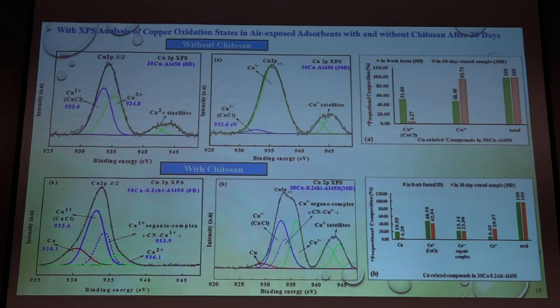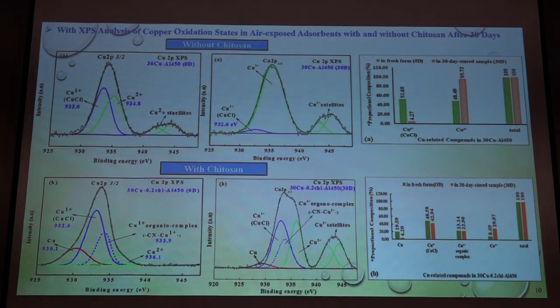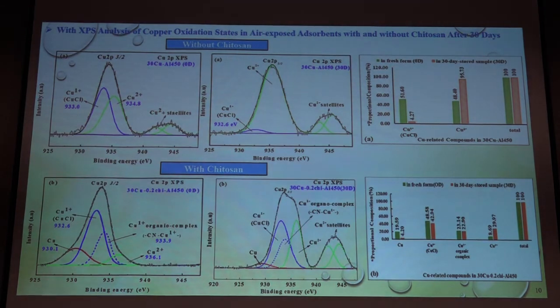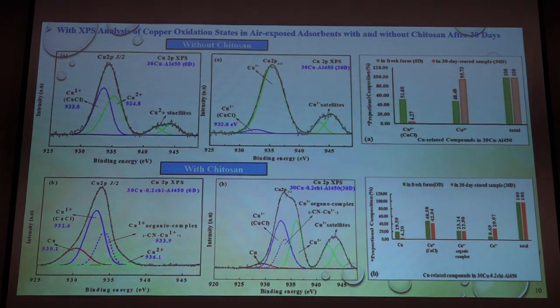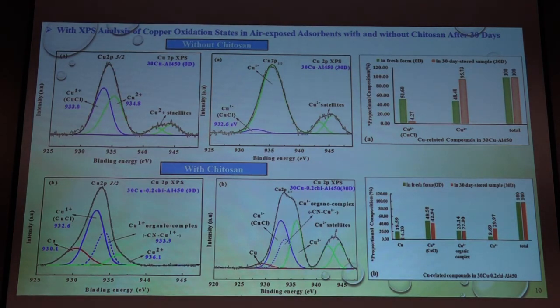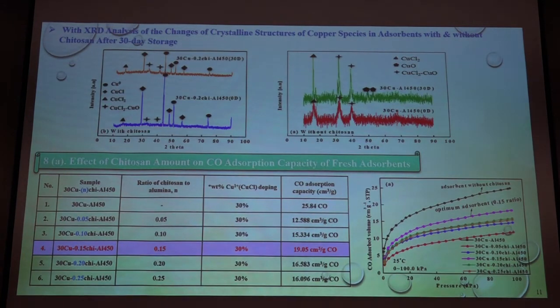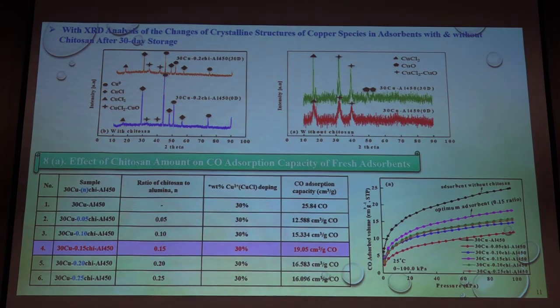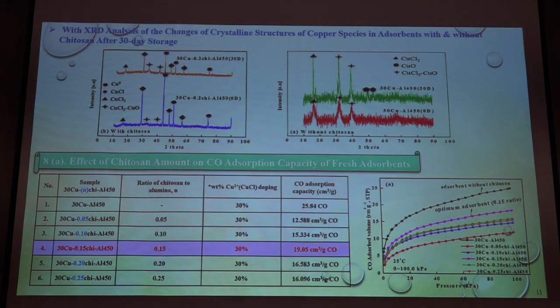Also, when I analyzed the copper ion oxidation state by the XPS spectrum in the blank sample without chitosan, its Cu1+ proportion decreased dramatically after 30 days of air exposure. But interestingly, in the chitosan-modified samples, the Cu1+ proportion decreased only slightly. That may be because of the formation of the copper 1+ complex with the nitrogen from the chitosan. Also in the XRD spectrum, I can still detect the CuCl peak in the modified chitosan sample.